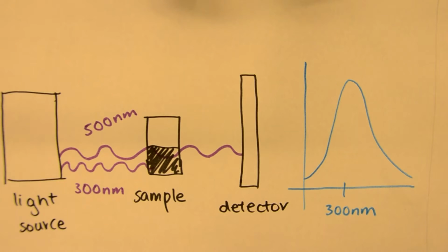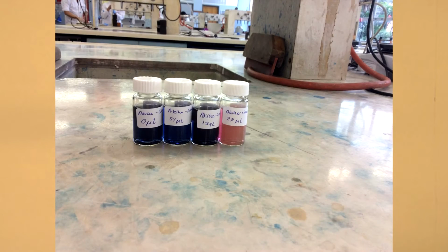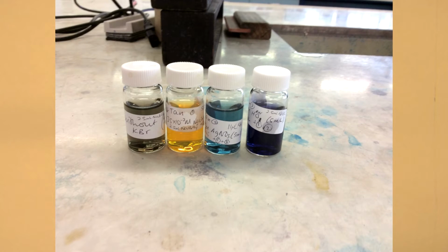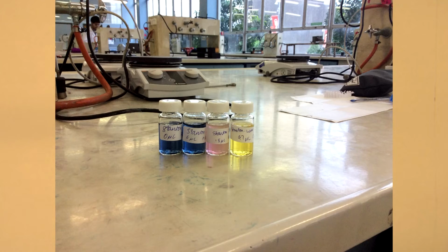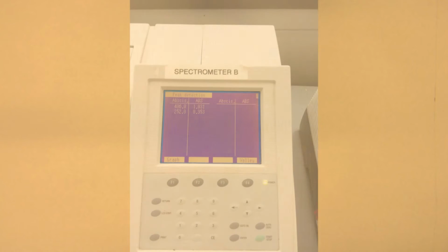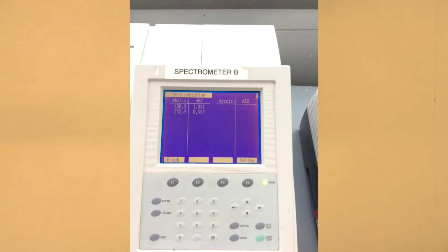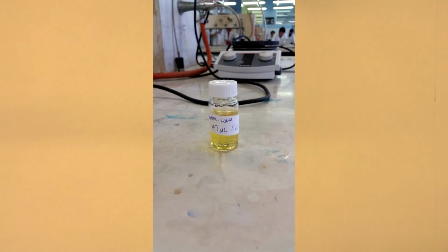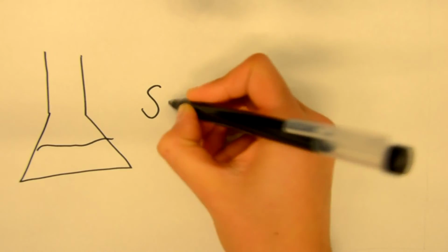As the size of nanoparticles changes, so does the wavelength of the electron oscillation, and thus their plasmon resonance. This means that nanoparticles of different sizes have different maximum wavelengths and appear as different colors. The most commonly prepared silver nanoparticle has a plasmon resonance maximum wavelength of around 400 nanometers and a distinct yellow color. However, the size of nanoparticles can be manipulated in a fairly simple experiment.